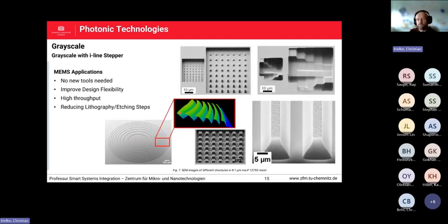And with our i-line tool, wafer level processes in high speed, high volume, let's say 1 minute per wafer, you can put every interesting 3D structure on the wafer and do not need E-beam or laser direct writing methods for this. And so we are going here to some results. For example, with MEMS applications, we have here pyramids. We produced needles. This one, for example, is a dose modulation layer, where we printed here 80%, 70, 60, down to 10%, and you see the resist height is enlarging to the top of the resist.